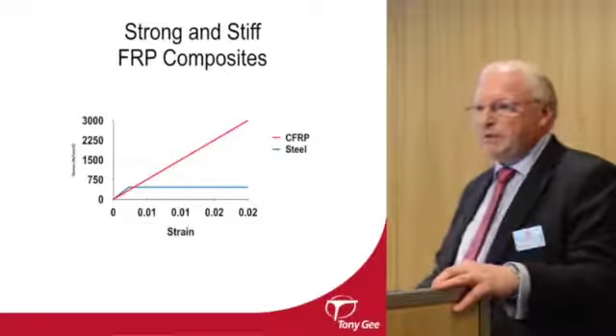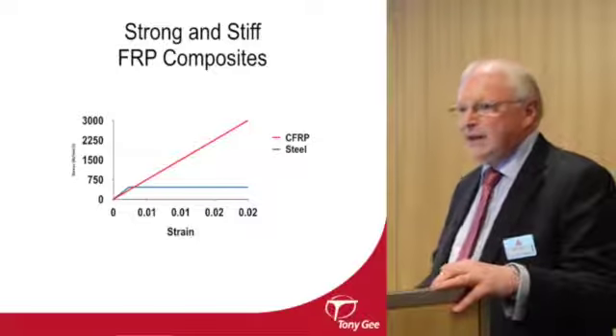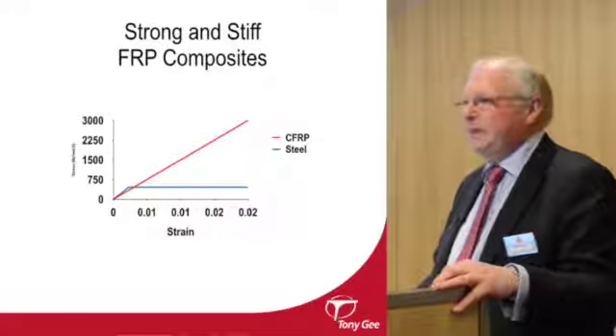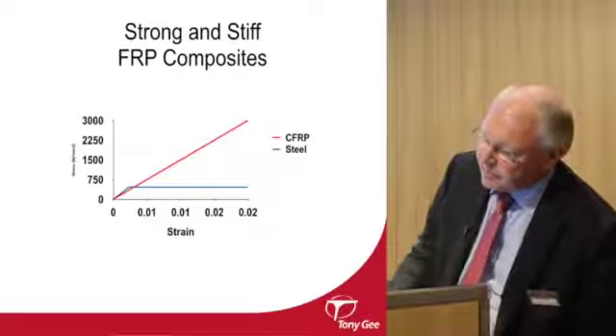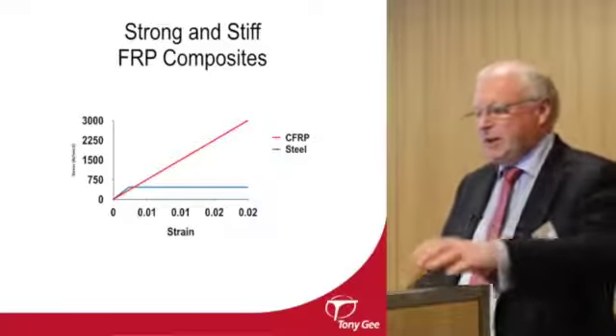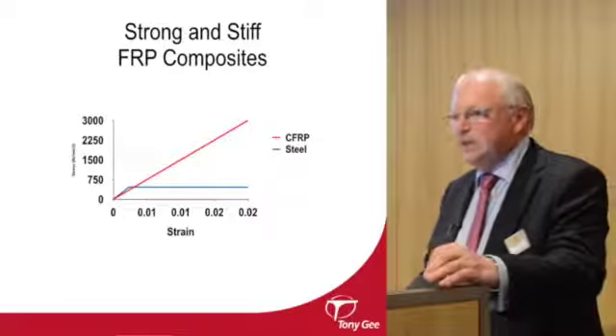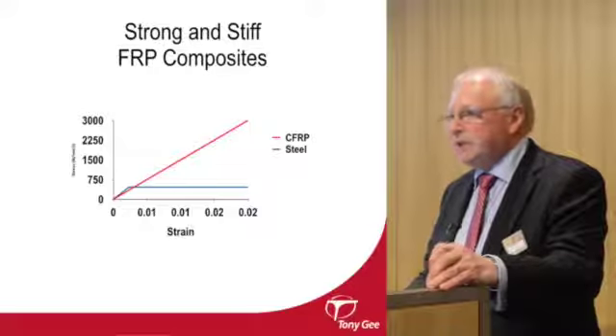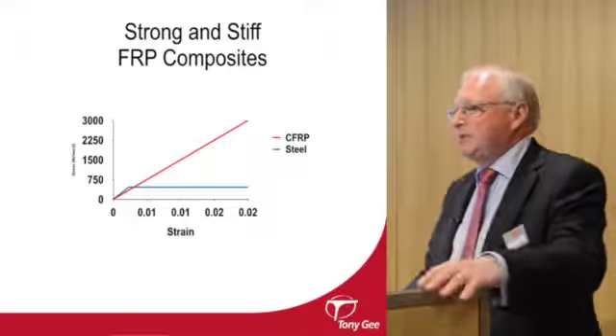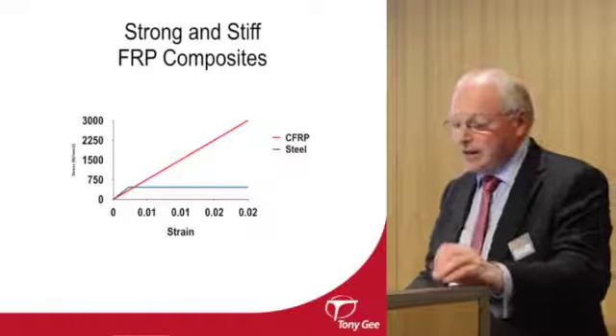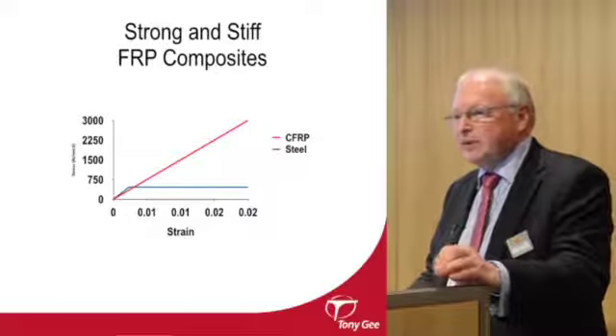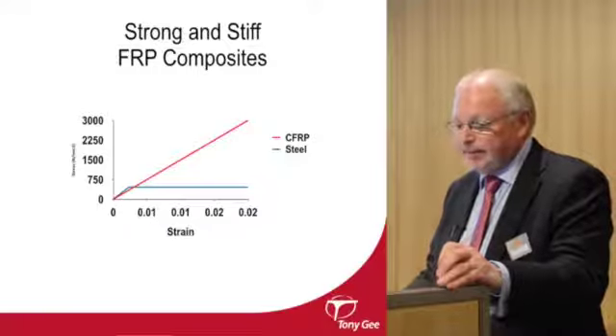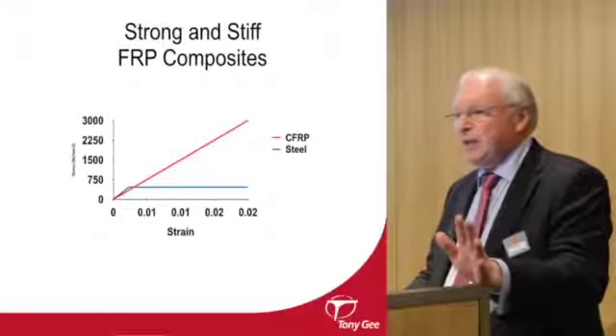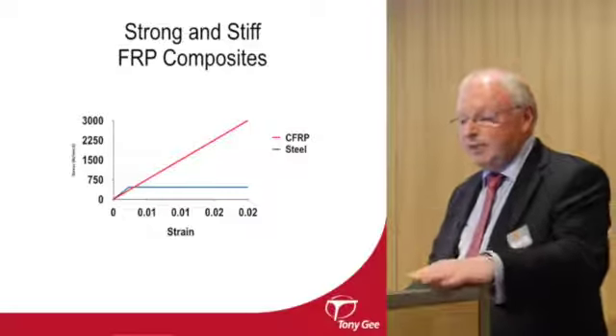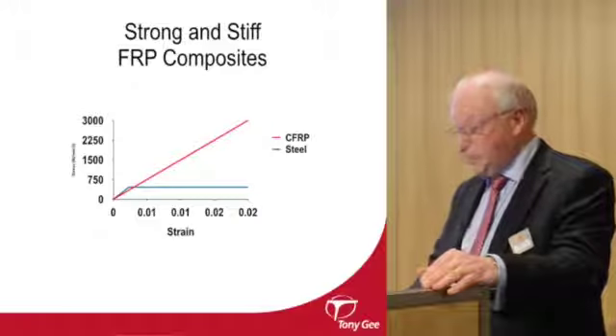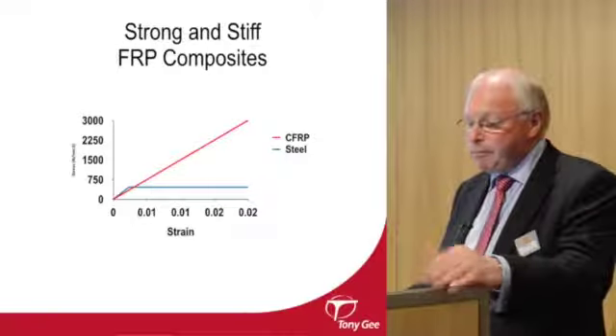From an engineering point of view, the materials are also great because they're linear elastic, so fairly easy to predict. Constant stress-strain relationship. On the downside, they don't have a yield plateau, so you need to be very careful at your operating level of strain because you won't get very much notice of failure. If indeed you were to fail the composite, more commonly you're likely to be limited by the bond to the material, be it concrete or steel.